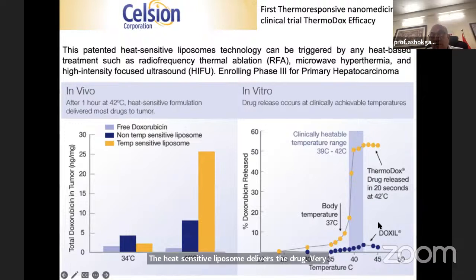If you look at 35 degrees, the heat-sensitive drug is barely above the free Doxil when the body temperature is 37. But if you take it up to 40, 41 degrees, the release is much sharper than the Doxil, which is in the free native state. The amount available is much less. So this is again a thermoresponsive drug which was developed by the Celsion Corporation.